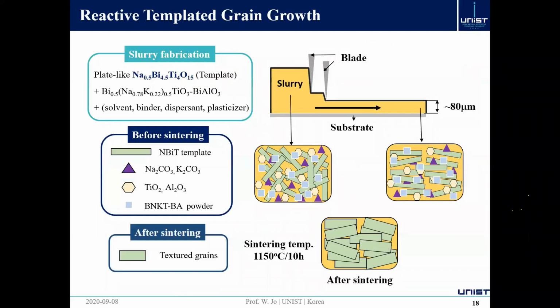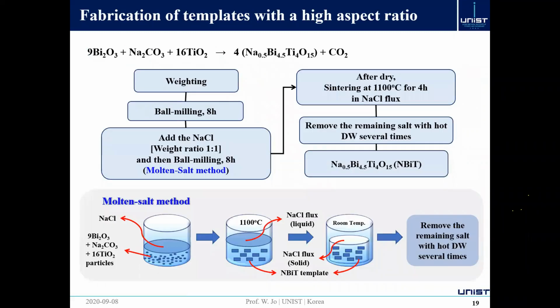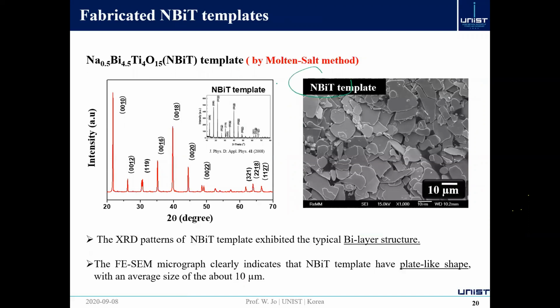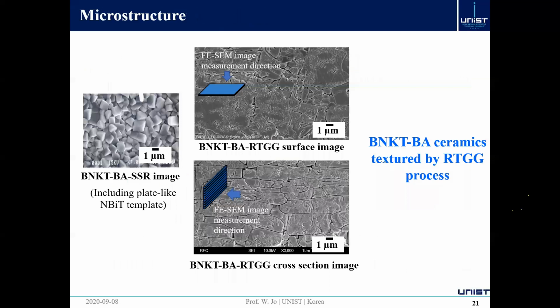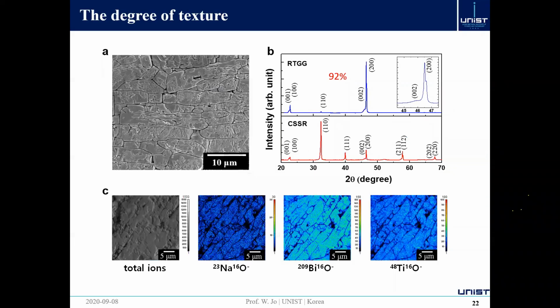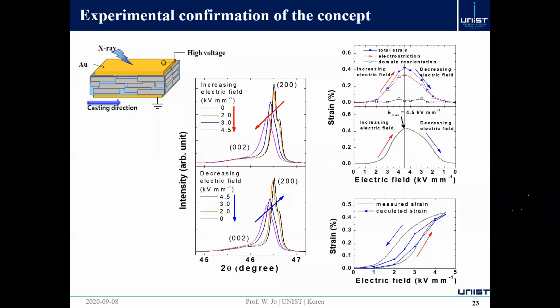So this is just an experimental procedure you can easily find in the reference I put in there. And here, this is the particle we used. This material is a ferroelectric with a spontaneous polarization direction along a or b. And as you can see, this SEM picture shows a highly textured, really well fabricated microstructure. And we did chemical analysis on that using SIMS, and we don't see any chemical inhomogeneity in this material.